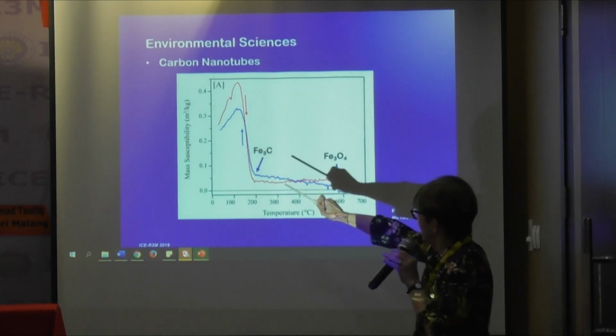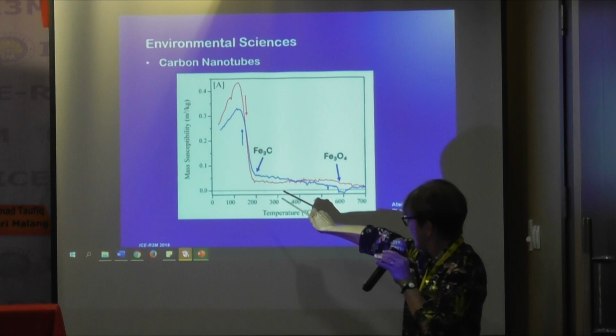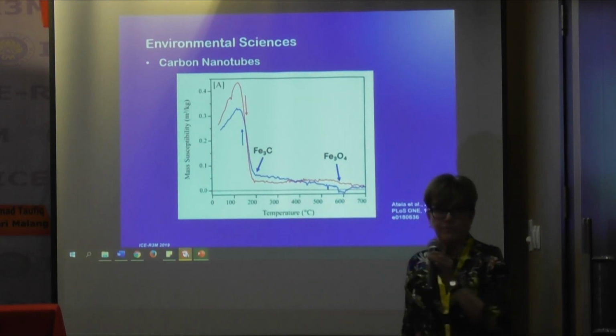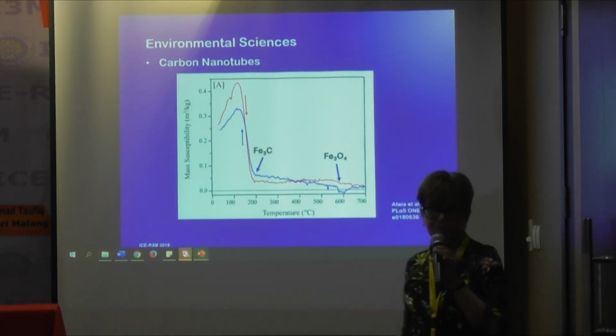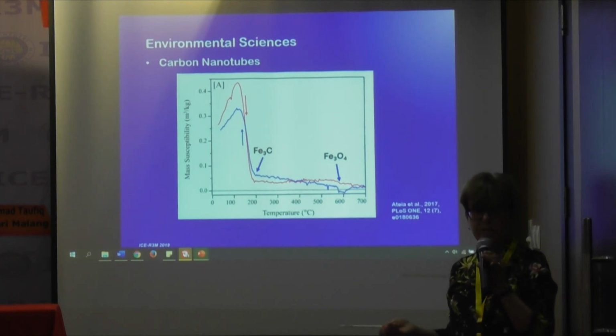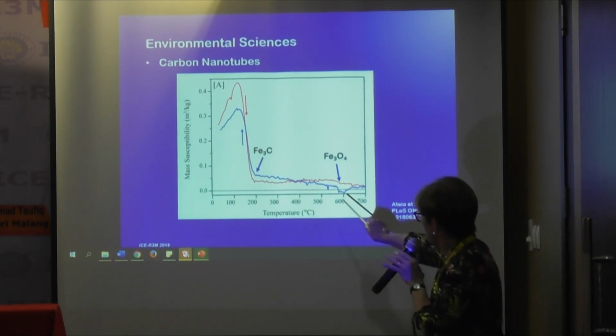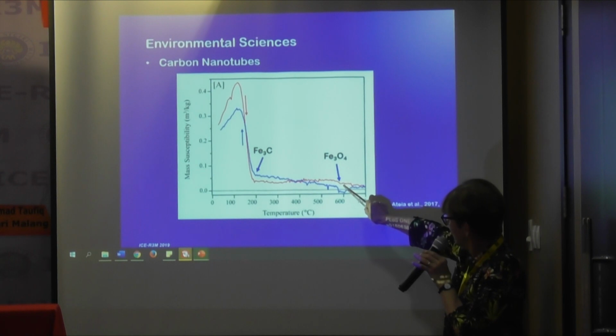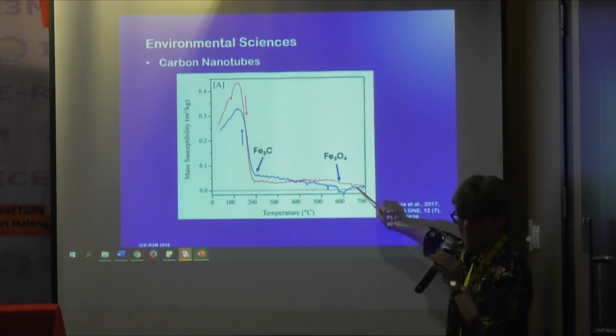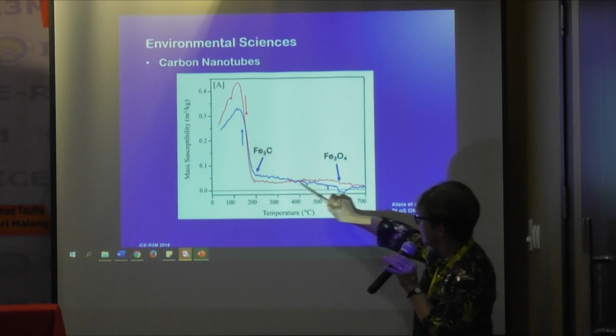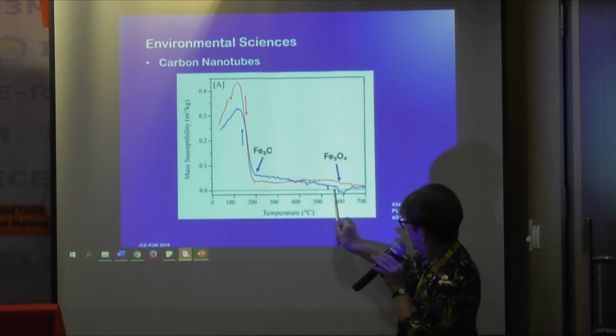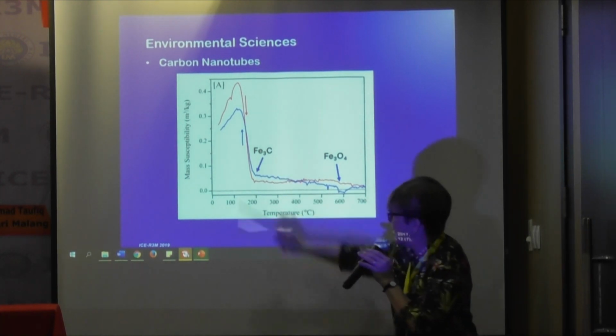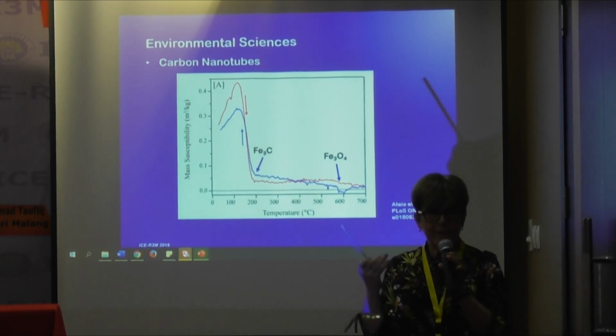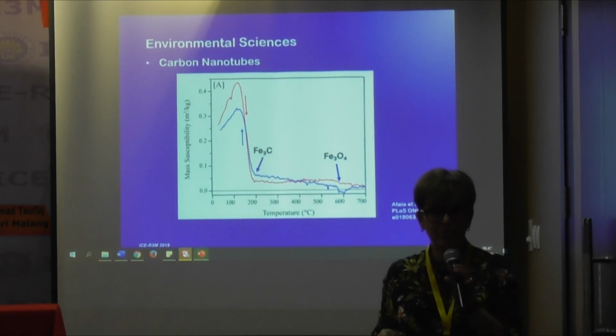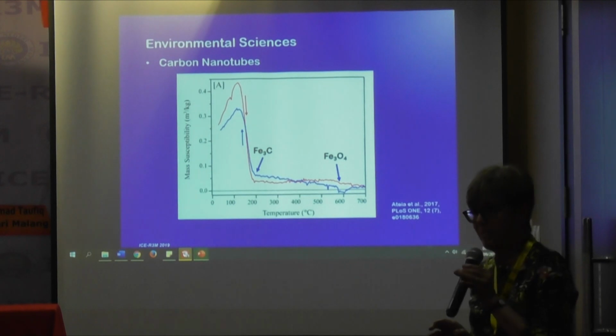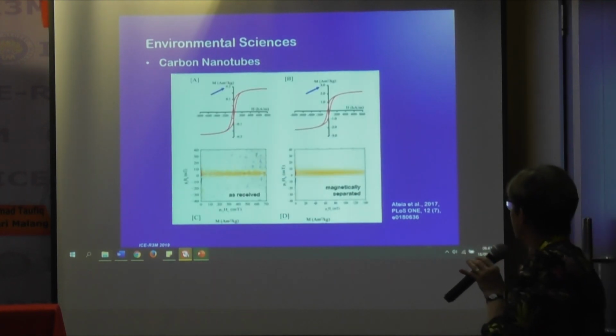So looking at susceptibility as a function of temperature here, you can see it drops very suddenly around, so we have something with a Curie temperature of 170 degrees Celsius. We see a little bump here that would be typical of magnetite, another one up here which may be maghemite. And then coming back, we lose a lot of this material in here, magnetite again. But the most material in there is, again, this cementite, this iron 3 carbon. So we said, okay, that's the magnetic material. Okay, next.